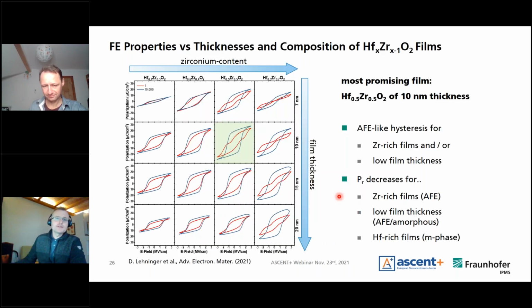So then some results. It is of course still mandatory to optimize the ferroelectric material, and there are certain factors, as I mentioned earlier, to get really good ferroelectric performance. First of all is leakage: we need low leakage currents, and we also like to maintain a large switching window. So we evaluated it here. We screened the zirconium content and also the film thickness. An optimum window or good performance was discovered in the range of 10 nanometer material thickness. If you add too high zirconium content, you end up in an anti-ferroelectric-like behavior, which means you don't have a remnant state. It switches back when you bias it to 0. So it's really a matter of optimization.